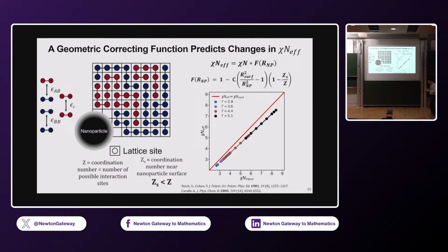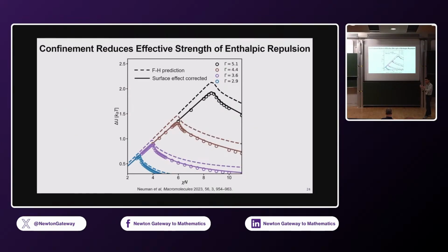So why is that? Basically, what's happening is right around the particles, I told you that there's this sigmoidal decay in the profile of the surface. So there are lattice sites that cannot be occupied by these monomers. That effectively decreases the coordination number of the polymers. So that's why you now have fewer AB contacts, and that's why the enthalpic interaction now favors the mixed state. We can now account for the surface effect, because we know exactly the geometry, and that's the solid line that you see. If we take into account the surface effect, we can look at how that affects the enthalpic interactions.